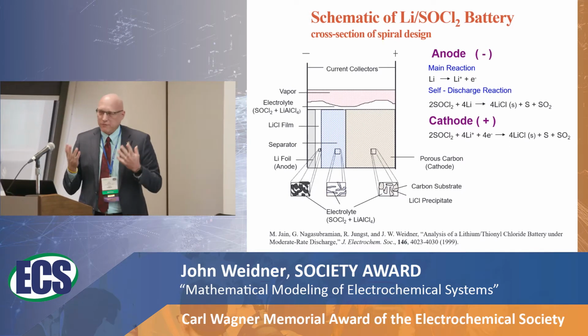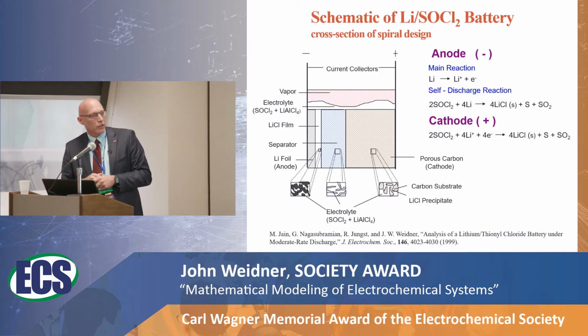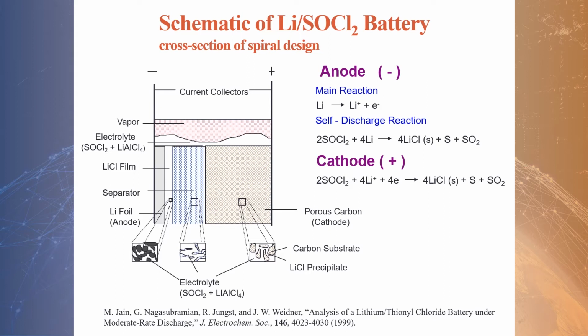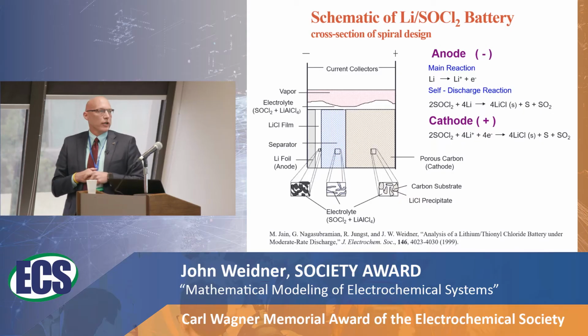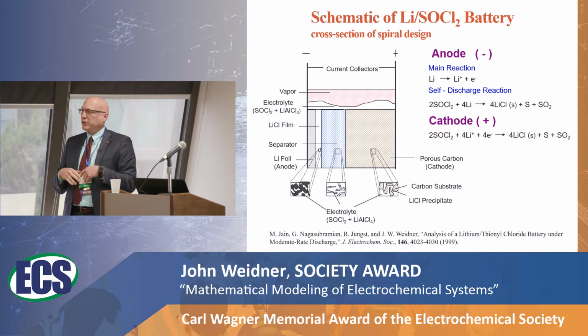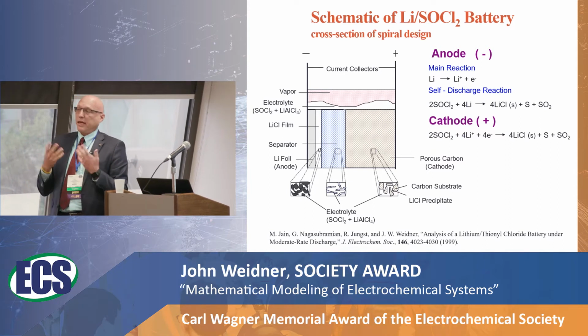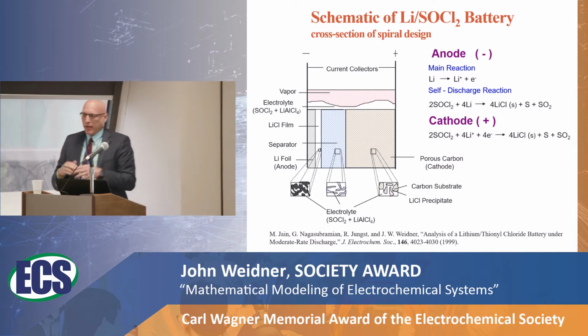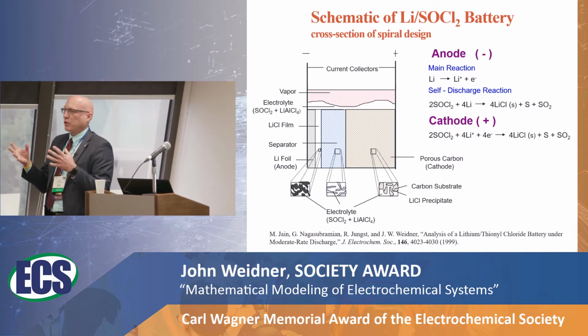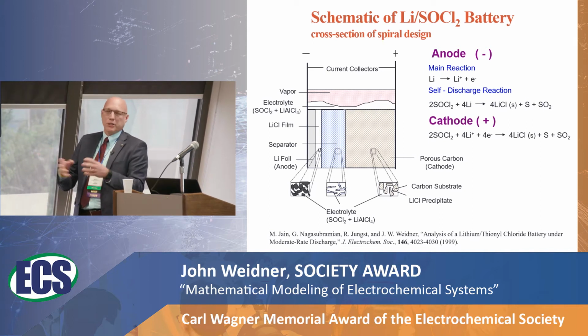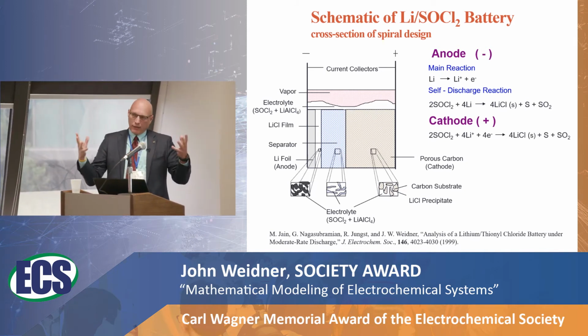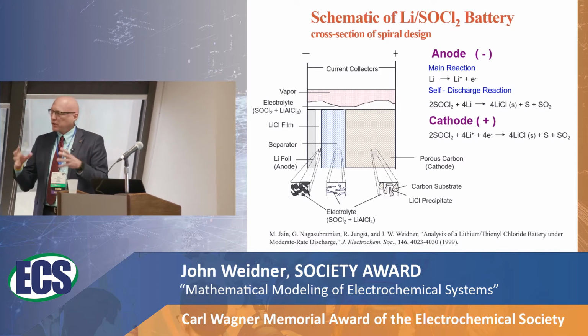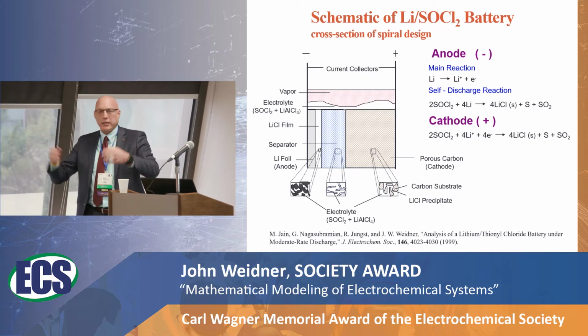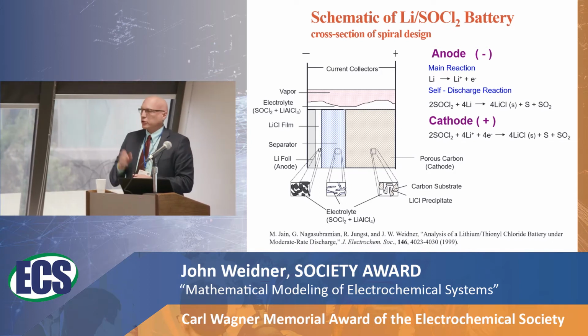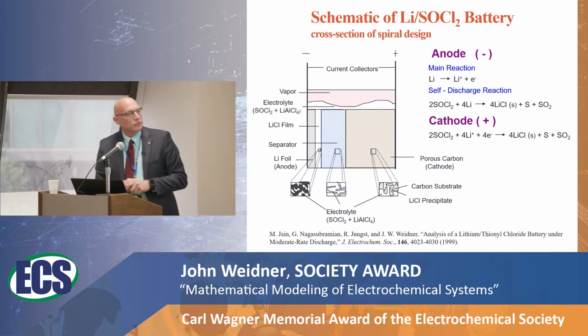So this system is a very high energy density primary battery, so you don't recharge it, but it's got a lithium anode, it's got a separator, and then a porous cathode, and the key reaction that we're trying to model on the cathode is the lithium chloride, which is a solid material. So that's precipitating inside the porous electrodes. This is a little different than the lithium ion electrodes that I'll show a little bit later, where we're intercalating lithium into the active material, and that solid phase is changing. Here, the porous carbon doesn't change, and we're depositing material at the site of the reaction. So wherever the reaction is occurring, you're getting a lot of solid material to deposit.